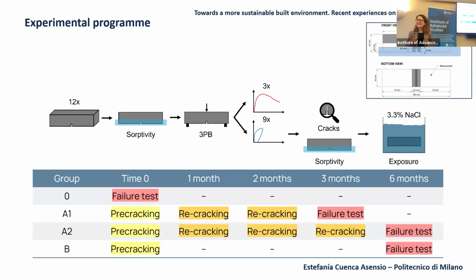I'm trying to explain this in a way for those people who are not so familiar with these things. Concrete has the ability to repair itself, that is self-healing, and this is really interesting in terms of durability, because if it repairs itself, the maintenance of the concrete structure is reduced, so it's more sustainable in this sense. Concrete has this property to repair itself, so we pre-crack the concrete and observe how the crack seals, also repairs, but only at the surface, by means of a digital microscope, taking pictures before and after the healing curing periods.